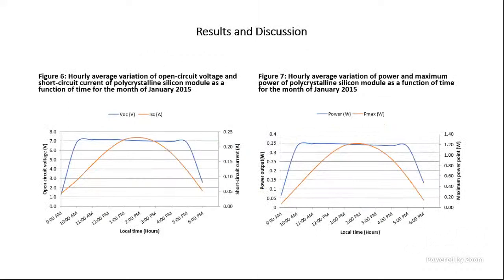Now, in figure 6, we see the hourly average variation of open circuit voltage and short circuit current of the polycrystalline silicon module as a function of time for the month of January, a typical dry season month. In it, we can see again that open circuit voltage peaks at early hours of the morning before the modules start heating up, while the short circuit current peaks in the afternoon when the module is already hot. And again, power traces the profile of open circuit voltage.